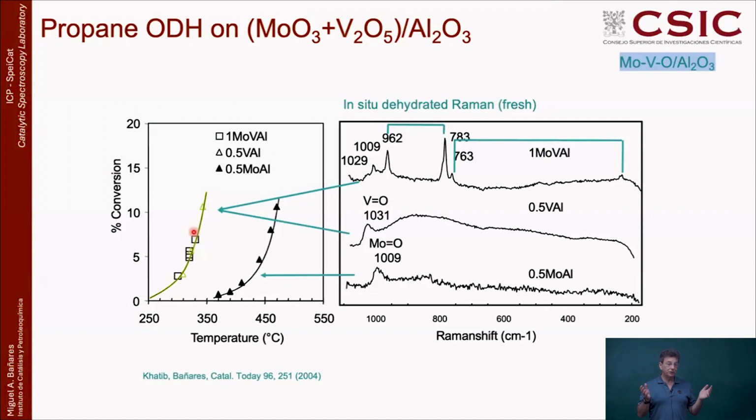And the total contribution of molybdenum is very low. Actually, at 200 plus, molybdenum affords a conversion near zero. So basically at this temperature, vanadium is giving a conversion and molybdenum is giving a negligible conversion. So basically you see no difference.